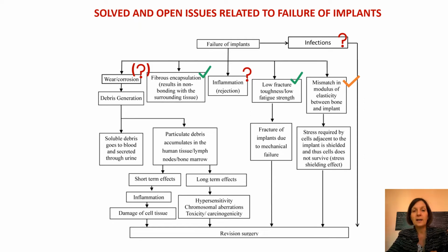We can see that there are some almost solved problems, such as the formation of fibrous encapsulation and problems related to fracture toughness and fatigue strength. There is a problem that is the mismatch in modulus of elasticity between bone and implant, so the stress shield effect, that is partially solved. And there are some open issues, such as infections and chronic inflammation and wear of the articular prosthesis. I will not face the last issues, but I will make an overview of the others.